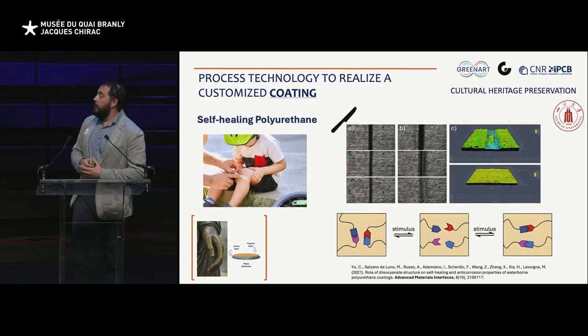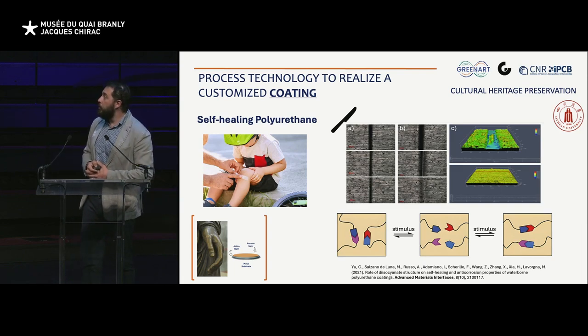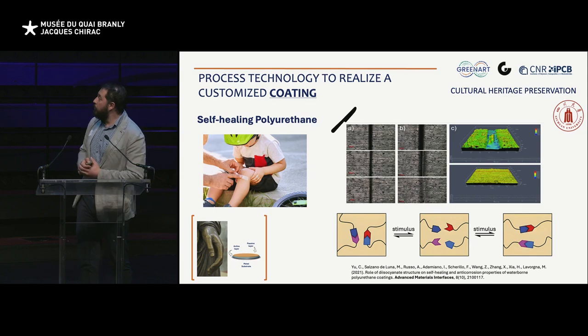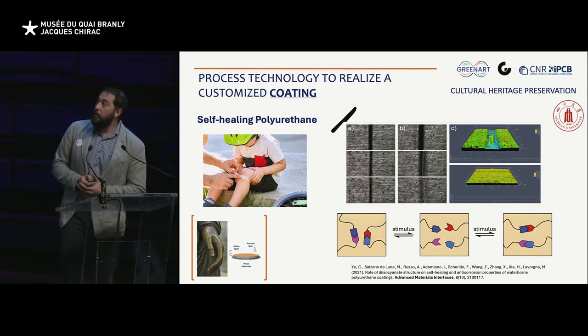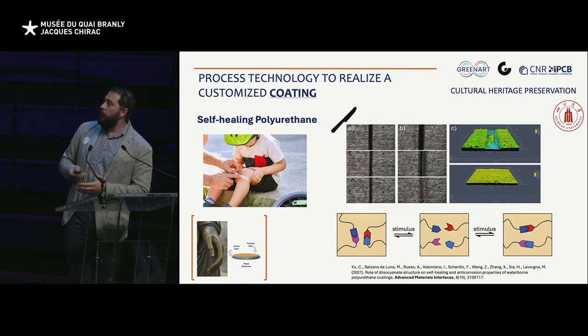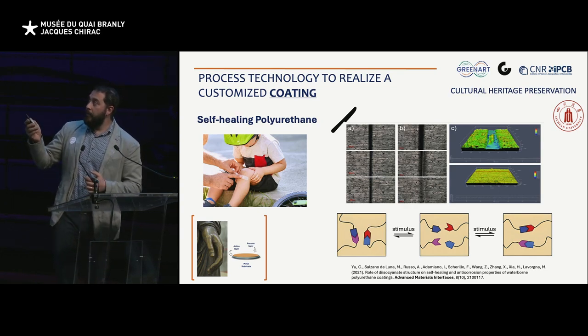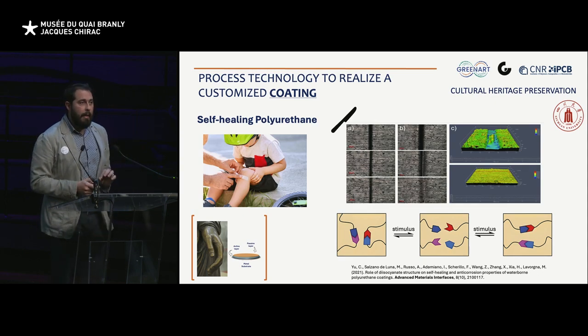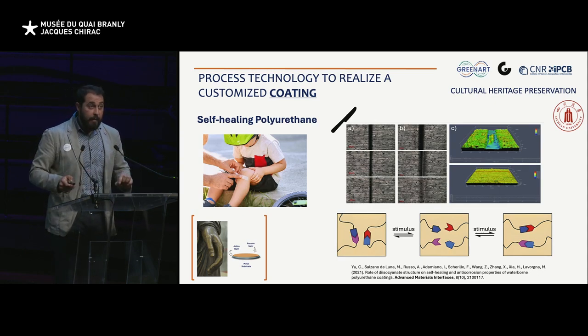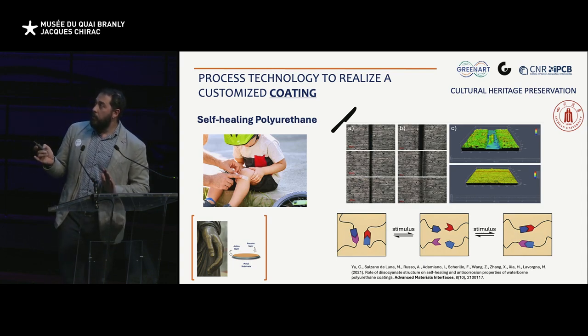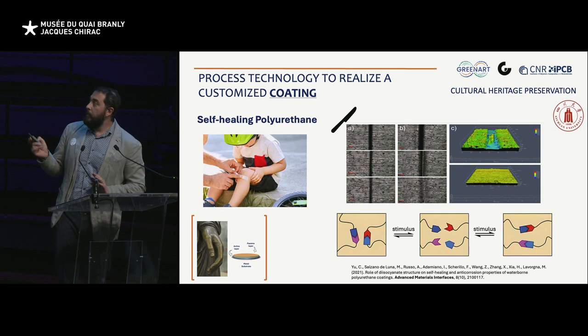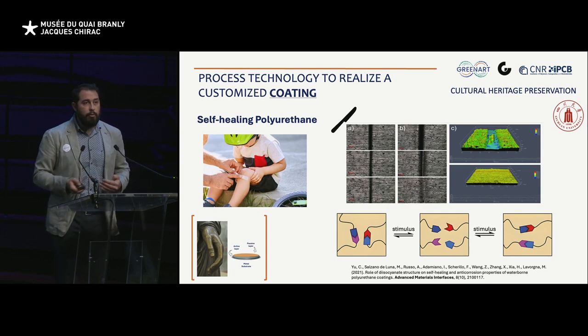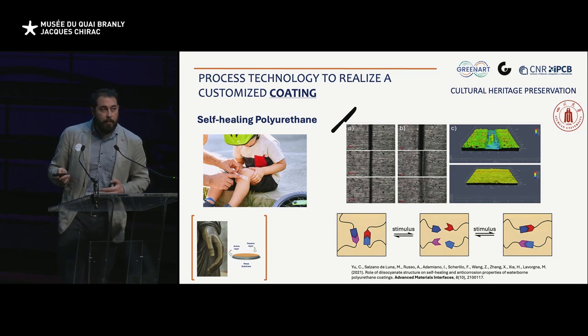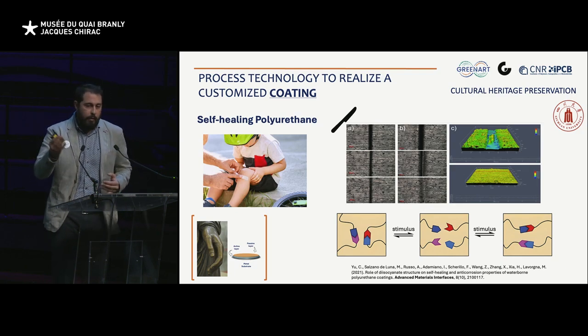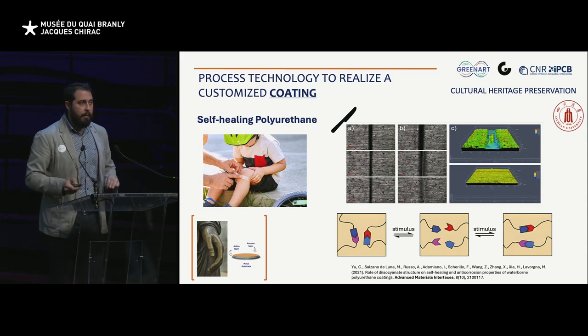So another way the coating is made is by self-healing polyurethane, that is quite self-explanatory because it is made of some building blocks that allow the material to be self-healed upon a thermal annealing. In this case, it was around 100 degrees. So when the surface undergoes a cut, it can recover its original shape, its original dimension, and in particular the cut, just by heating it up.